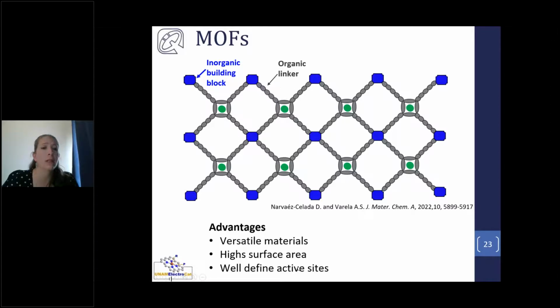So they are versatile materials, they have a high surface area, and they have well-defined active sites because I know exactly what the building blocks are that I'm using. So I know the nature of the active sites and I can tune it. In addition, these metal organic frameworks can have redox active sites, and these redox active sites can be useful for electrochemical applications. These redox sites allow electrical transport via redox hopping.